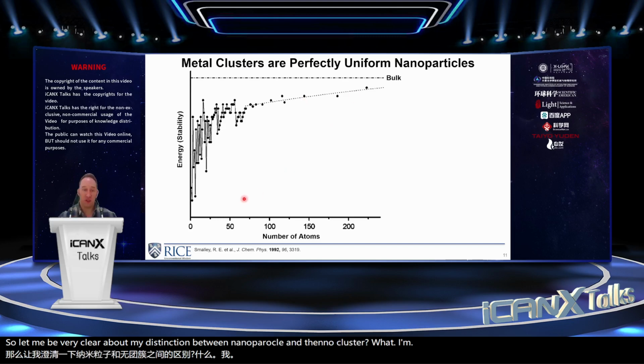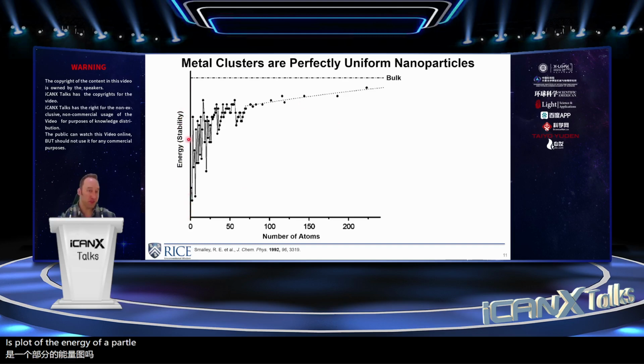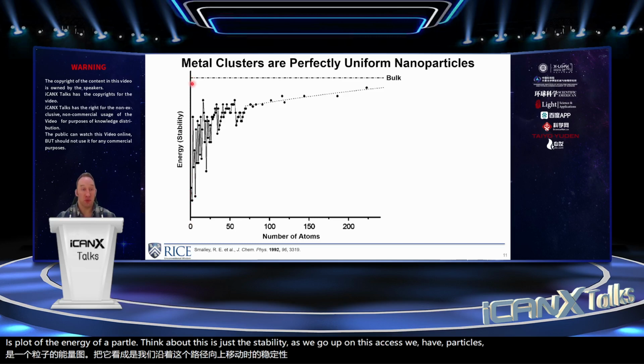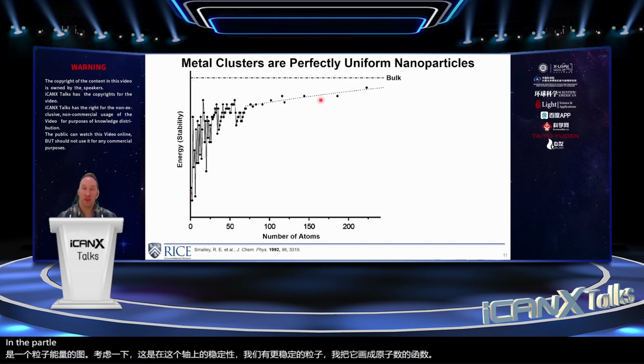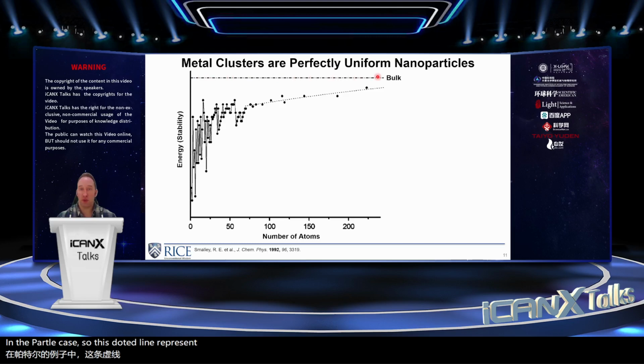What I'm showing here is a plot of the energy of a particle. Think about this as just the stability. As we go up on this axis, we have particles that are more stable, and I'm plotting that as a function of the number of atoms in the particle. Okay, so this dotted line represents a bulk crystal. That's kind of the equilibrium state.